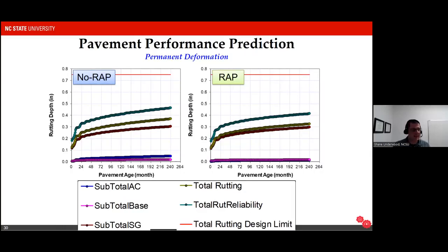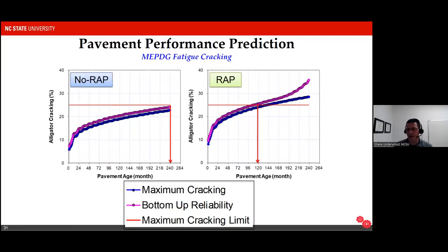In the case of fatigue, however, we see a different behavior. In this case, we have cracking reaching about 25% in the no RAP case at the end of a 20-year period. But the RAP case, we actually reached that same cracking threshold in about half the time. So in this case, using the RAP-based material has a negative consequence of increasing the cracking propensity of the material.